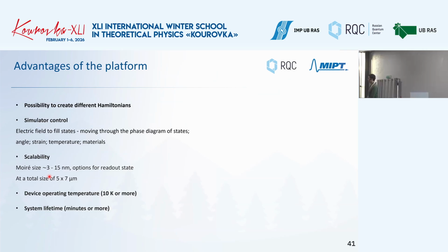Thank you very much for your question. It is definitely true for the polarization dependence, and this indeed we checked. We measured with linear, circular, and so on, and this is one of the key explanations why we think so. The dependence on the polarization is one of the key explanations in our case for the mechanism of the photodetection. Definitely there is a dependence, and depending on which type of detection mechanism you have, the dependence will be different. And regarding the K vector, it's a nice idea, but we did not try it and did not consider this. But in general, it is possible to modify the setup and to measure this case, I think.